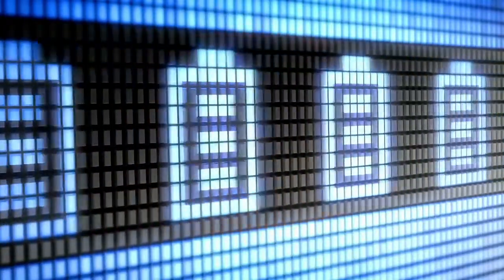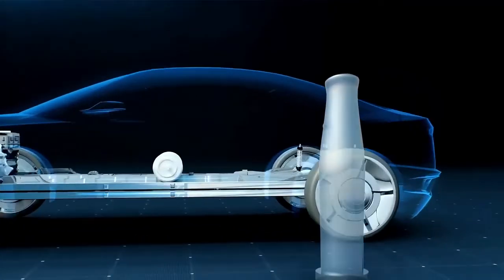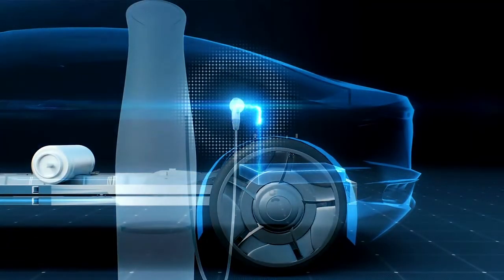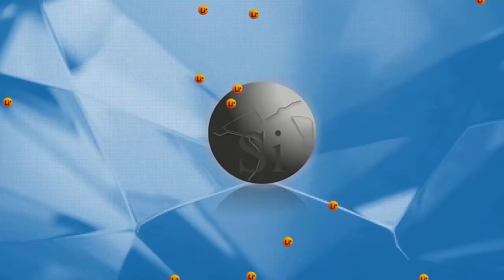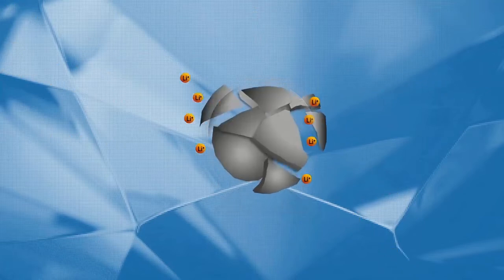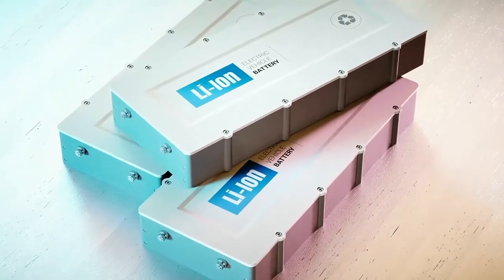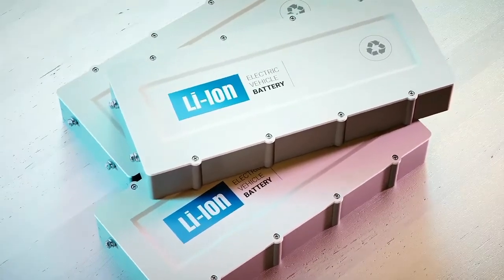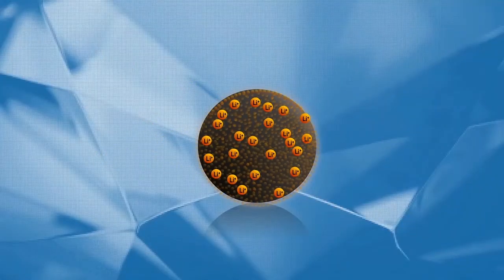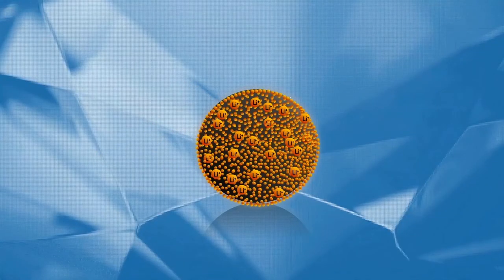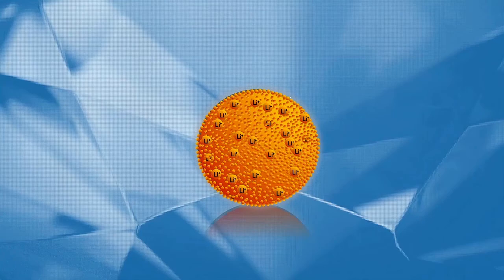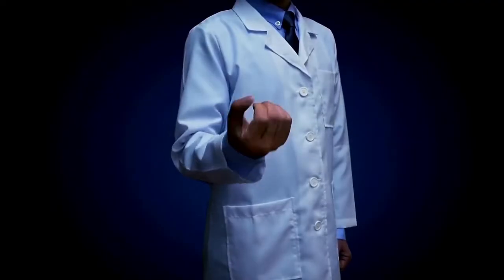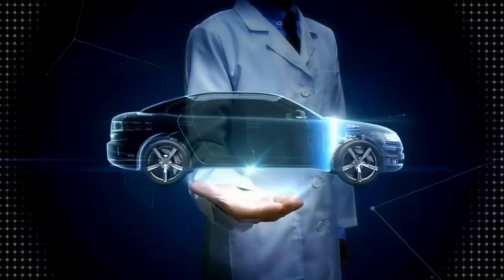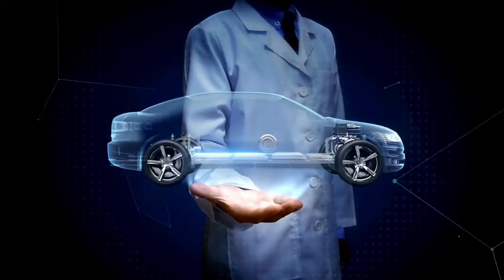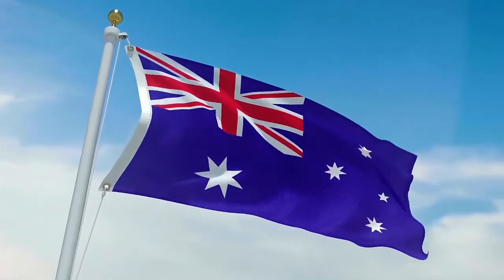However, metallurgical silicon is unable to be used in commercial lithium-ion batteries today due to two major technological barriers. Silicon expands up to 300% in volume during battery operation, causing swelling, fracturing, and battery failure. The second challenge is that silicon deactivates up to 50% of the lithium ions in a battery. Called first cycle loss, lithium ions are rendered inactive by the silicon, immediately reducing battery performance and life. Industry has been in a race to crack the silicon code, but Australia appears to be at the forefront of the race.